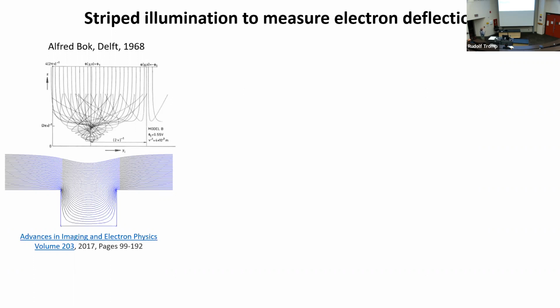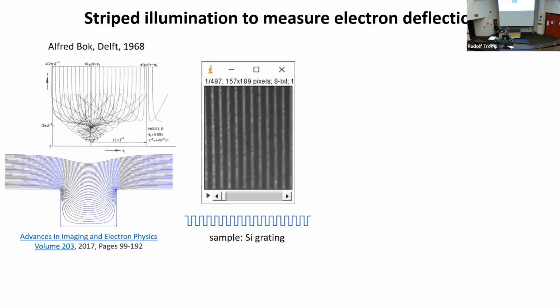He used the cosine potential. And you see, if you come in exactly along this symmetry line, of course, the electron just comes right back because the derivative, the in-plane component, is 0 here. But when you go to the edge, then the electron feels this field gradient in the horizontal direction here and is deflected sideways. So the electron undergoes a deflection angle, right? Of course, that's symmetric.